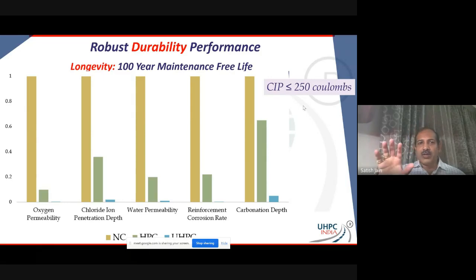And if I forget to tell you this later, concrete is brittle and explosive when you do a compression test on very, very high strength concrete. But with UHPC, you no longer have that because of the presence of the steel fibers.